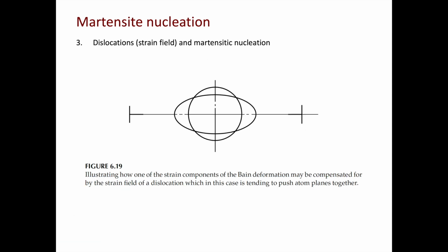In addition to the dislocation core, the strain field around dislocations is believed to affect martensite nucleation as well. In the example shown here, there's a dislocation dipole, and the region between those two dislocations is highly strained, and the strain can favor martensitic transformation as well. It is interesting to mention that external strain can play a huge role on the martensite variant. If you apply an external load on the material while cooling down, the martensite variants you obtain here will be different from the strain-free condition.